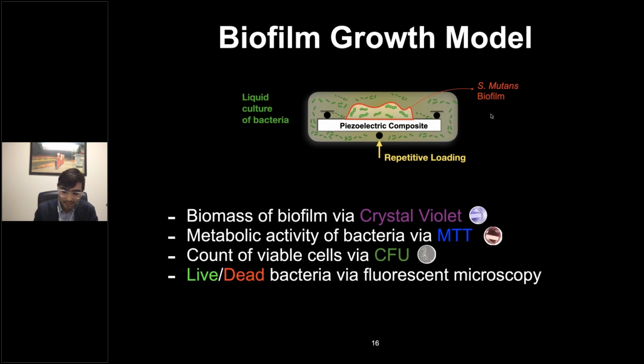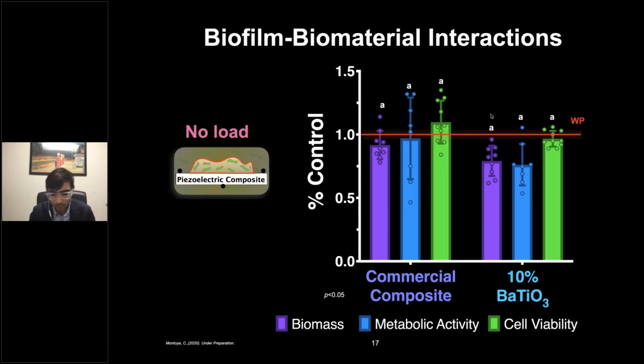To evaluate the antibacterial effect, we conducted four tests. We measured the biomass of the biofilm - literally measuring the weight of this biomass. We also assessed the metabolic activity that the bacteria is promoting, counted the viable cells, and did some fluorescent microscopy.